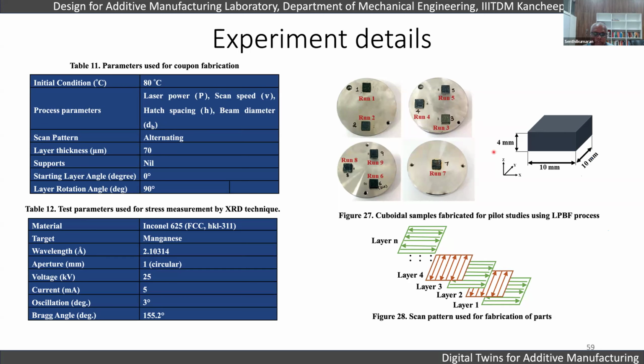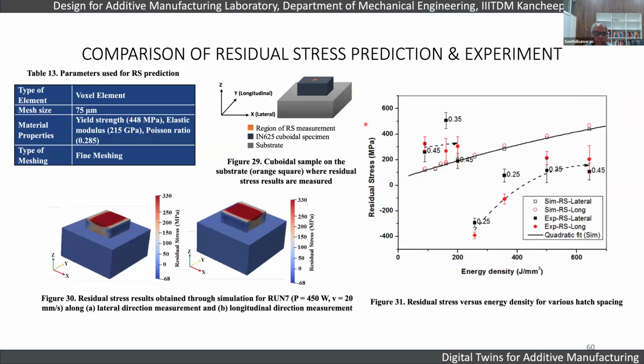So we used this particular kind of scan pattern and did a few experiments with Inconel 625, and to our surprise, some of the commercial tools were not able to give the residual stress predictions. For example, we used a few commercial tools. I don't want to name them. For simulating the residual stresses with FEM, we used ANSYS, but for microstructure and distortion simulations, we tried a few commercial solutions, like the ones I have shown there.